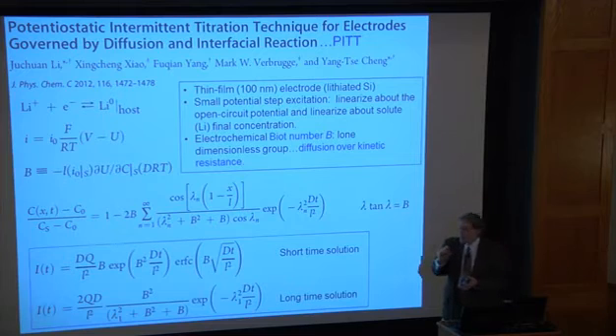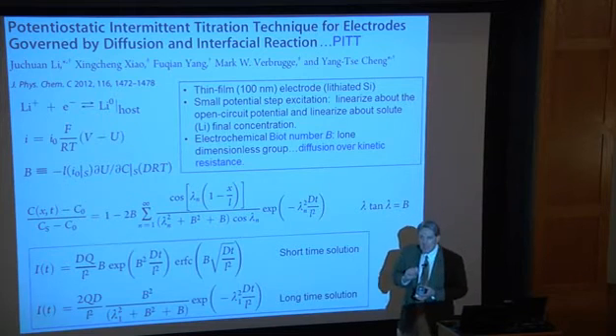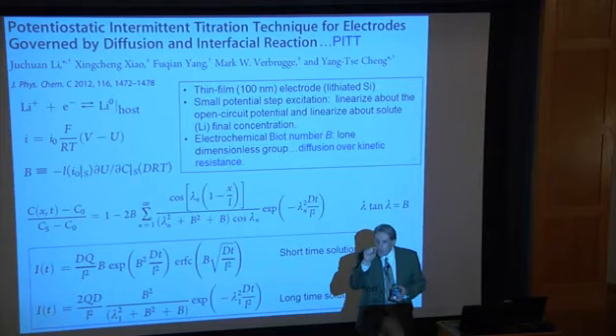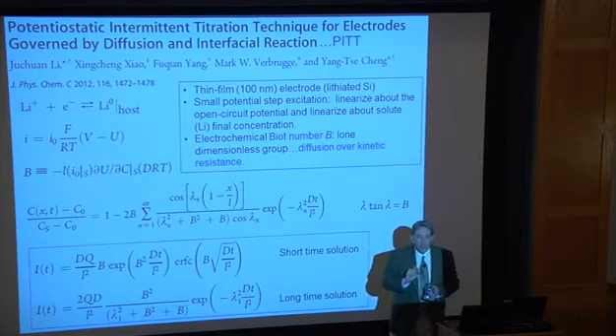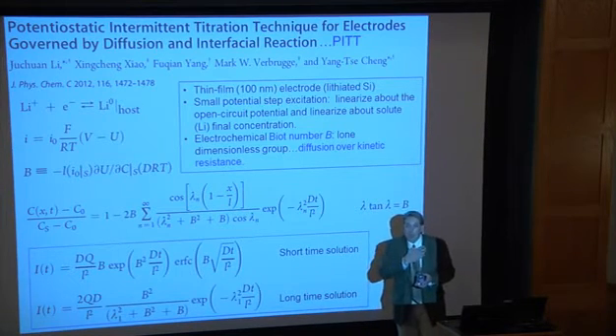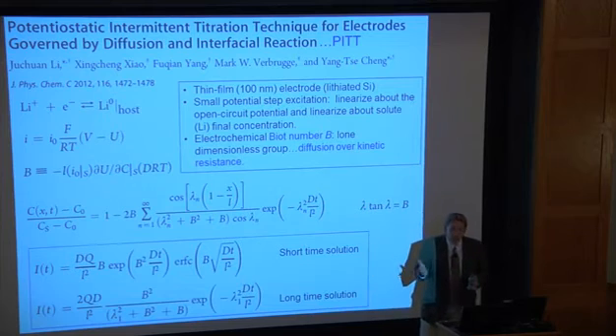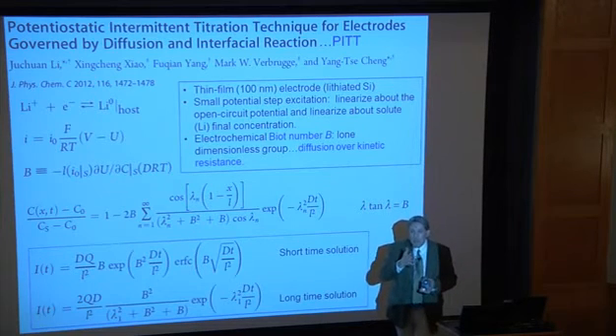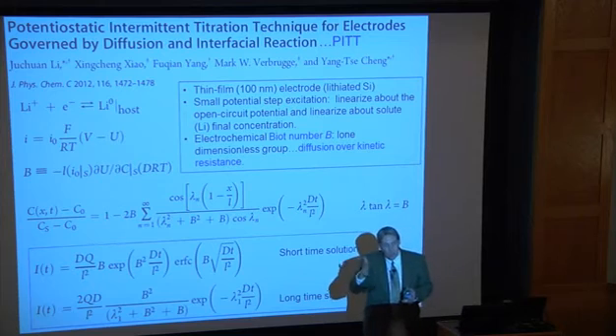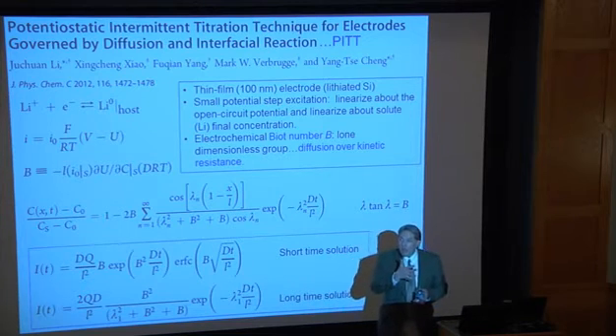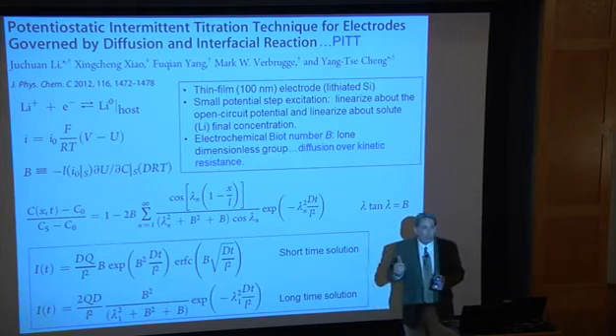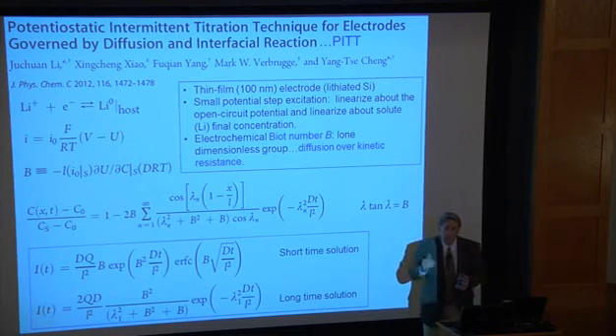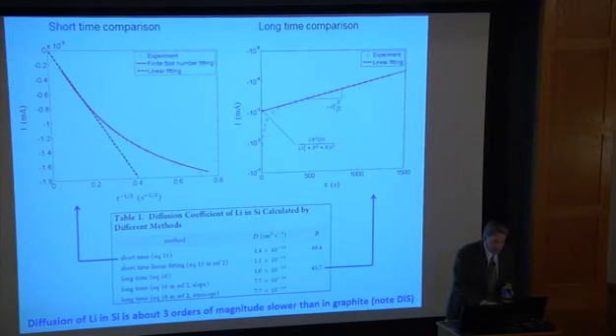PITT, by its nature, is a small-scale potential excitation. You use about 5 millivolts. Because you use such a small scale for your excitation, you can linearize your transport equations and your whole system of equations, and you get analytic solutions. And you don't need to worry about variations of the effective diffusion coefficient, that term I showed earlier, intruding on your transport equations, because you're linearizing about small fluctuations in concentration.